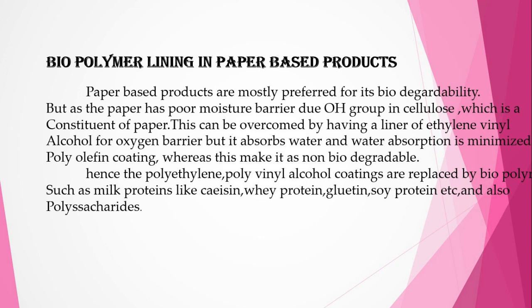Next is biopolymer lining in paper-based products. Paper-based products are preferred for their biodegradability, but paper has poor moisture barrier properties due to the presence of free OH groups in cellulose. This problem is overcome by using a liner of ethylene vinyl alcohol (EVOH) for oxygen barrier, though it absorbs moisture. Water absorption is minimized by a polyolefin coating, which makes the material non-biodegradable. Hence, polyethylene and polyvinyl alcohol coatings are being replaced by biopolymers such as milk proteins like casein, whey protein, gluten, and soy protein.